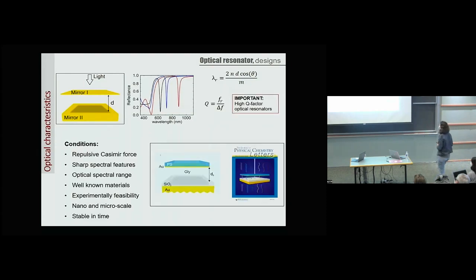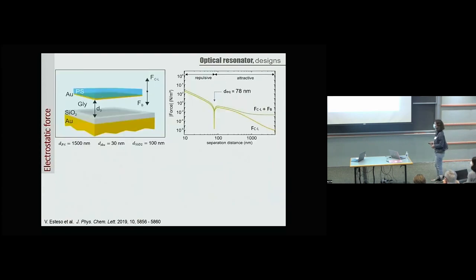So in our design, one of the most important things was to create high Q factor optical resonators, and they had to fulfill all these conditions. We wanted repulsive Casimir forces with sharp spectral features in the optical regime, with well-known materials that we could handle in the lab and that we could do our estimations with, everything in the microscale, and stable in time. So here I show you some results for some representative geometrical parameters, because the final design is something like this. We have a bilayer of polystyrene with a thin layer of gold immersed in glycerol over a silica film on top of a gold substrate.